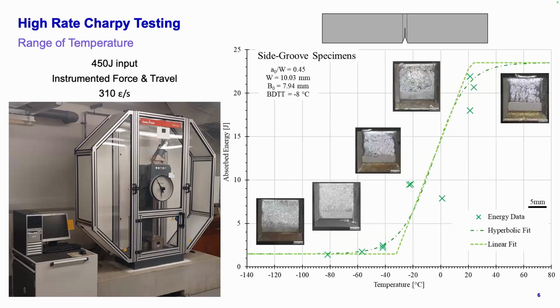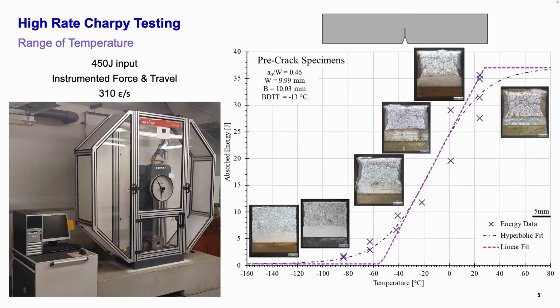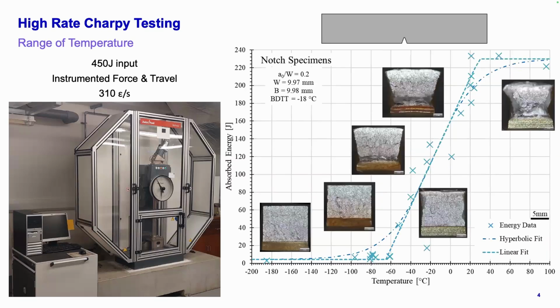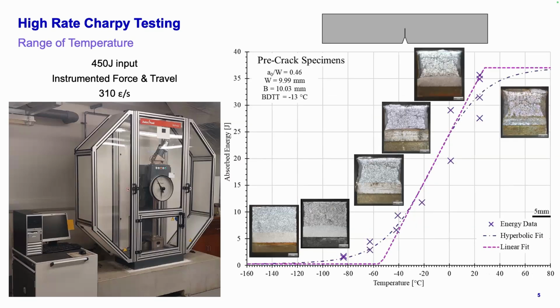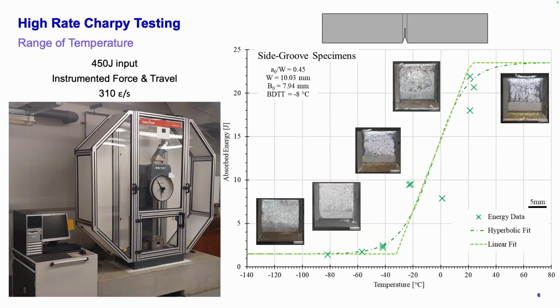And finally, the highest constraint. We've been steadily increasing in brittle ductile transition by quite small amounts, granted, but it is increasing. So from -18 to -13 to -8. So it's increasing the transition temperature and reducing that energy requirement. It's quite nice. We've got some good testing out of there showing that the fracture energy required with our different constraints is reducing the amount of energy required, reduced toughness. For the same material, just changing the geometric constraint.